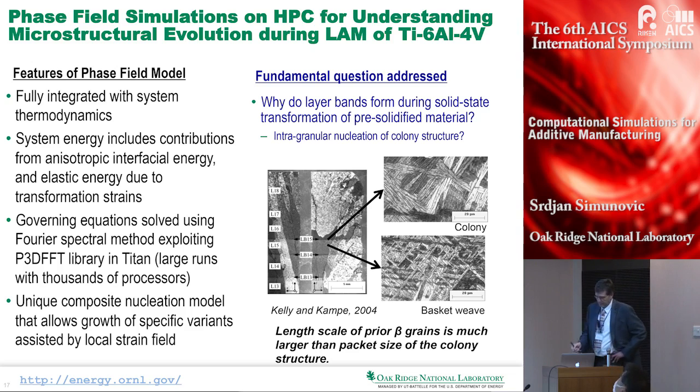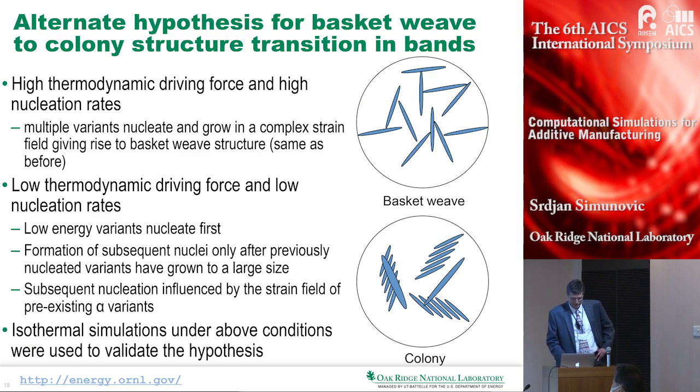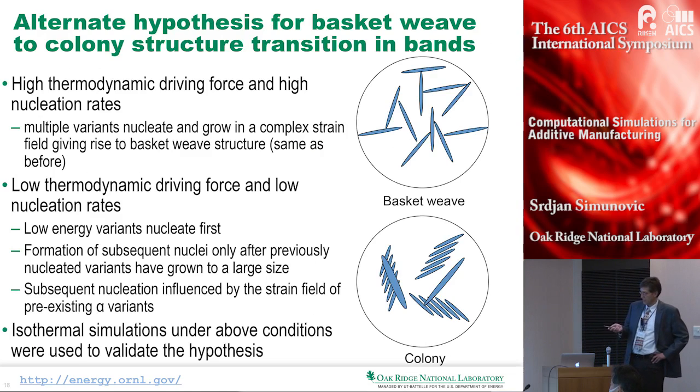We use a high performance implementation of the phase field method and try different assumptions. One of the assumptions was that this difference between the basket weave and the colony shape were driven by the thermodynamic driving forces and different nucleation rates that the material experiences as these layers are being grown and then reheated and going through cooling and heating process again.